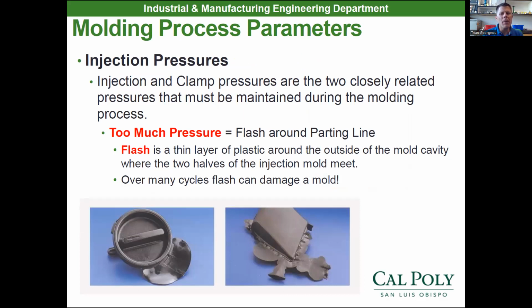Now, if we had too much injection pressure and we didn't have enough clamping force on our molds, we're going to get flash around the parting line. Flash can ruin your molds. If you flash too many times, you can actually flex the mold and damage it. Basically, you have fluid flowing over a surface and you're deforming the mold. So you're getting a thin layer of plastic around the outside of the mold cavity where the two halves of the mold meet. Flash is a very bad thing.